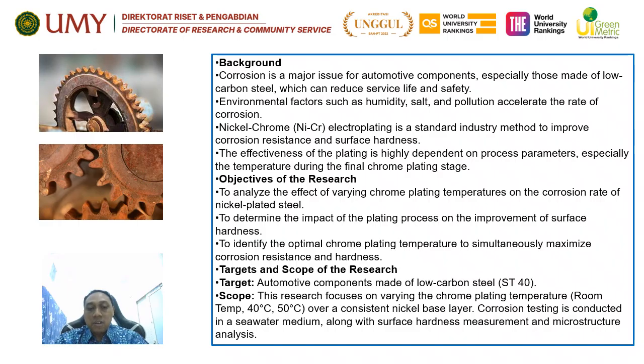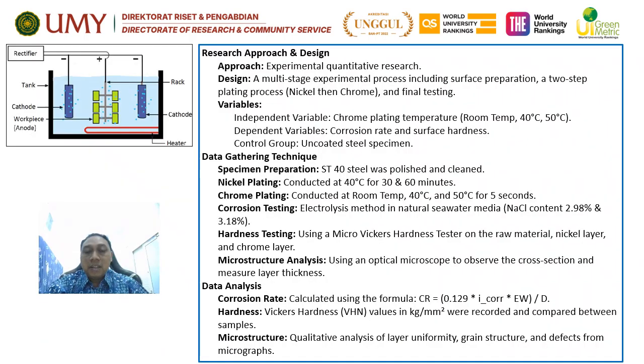The objective of the research is to analyze the effect of varying chrome plating temperature on the corrosion rate of the nickel plated steel. The scope is that the research focuses on varying the chrome plating temperature at 25 degrees Celsius, 40 degrees Celsius, and 50 degrees Celsius. The research approach and design is a multi-stage experimental process including surface preparation, a two-step plating process, the nickel and then chrome, and final testing.